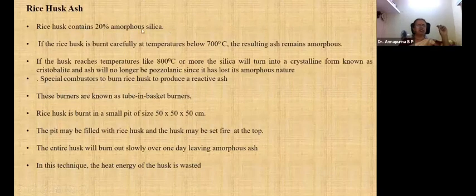It contains 20% amorphous silica. It has to be burned carefully at a controlled temperature up to 700 degrees centigrade. But if the temperature is raised above 700 degrees centigrade, and it is burnt at 800 degrees centigrade, the material turns into crystalline form and it cannot be used as a pozzolanic material. So it has to be burned at a controlled temperature.